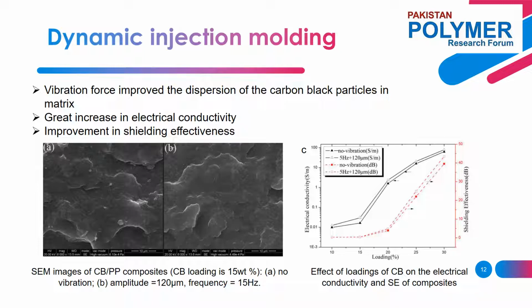The density of particle distribution is not big enough for the formation of a conductive network, because particles can aggregate easily in the molding processing. Figure B shows a micrograph of the carbon black and polypropylene nanocomposite with the application of vibration force. It can be seen that the dispersion of carbon black particles in the matrix has improved significantly. The average particle size of carbon black decreased greatly because the blending of the melt was enhanced.